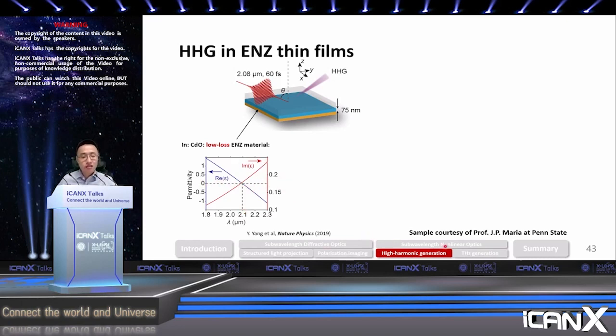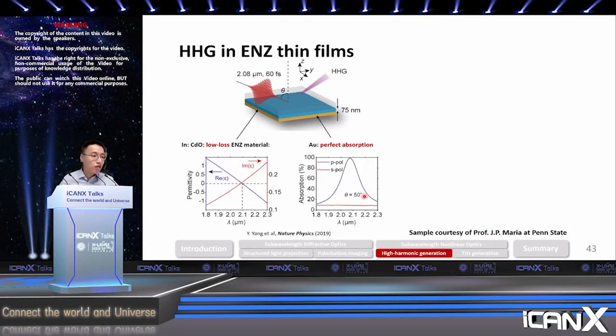This sample is grown for us by our collaborator, Professor Jon-Paul Maria's group, now at Penn State University. On our sample, we further added a layer of gold to further enhance light-matter interaction inside the cadmium oxide layer. For the experiment, we shine a femtosecond laser at the ENZ wavelength of CdO, and we measure the high harmonic generation on the reflection side.